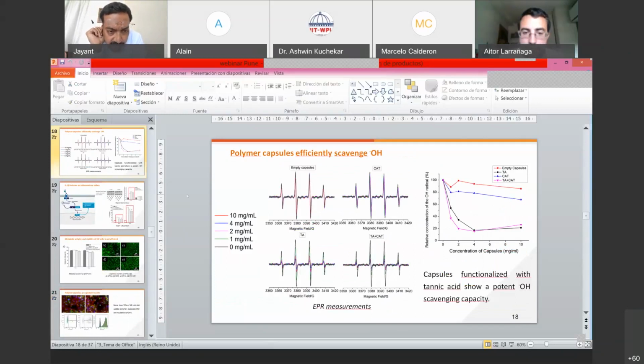So that magnetic field, which is on your x-axis, which is very indicative of a high magnetic field. So where is this magnetic field coming from? No, this experiment is quite similar to NMR analysis, but you are checking other aspects, in this case the hydroxyl radical, right? This experiment we only performed to confirm that our capsules were able to scavenge hydroxyl radicals. So the hydroxyl radicals, when you bind them to a paramagnetic molecule, give you this kind of signal. And then you check how this signal is being reduced as you incubate with your capsules. And this means that the hydroxyl radical is being scavenged. So it's not talking about the paramagnetic properties of your capsule.